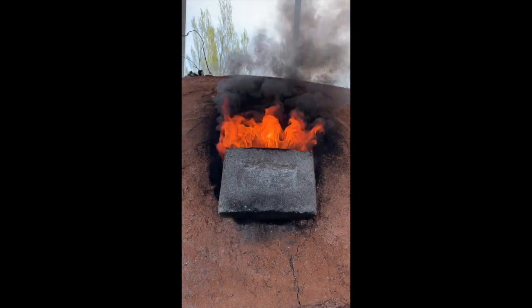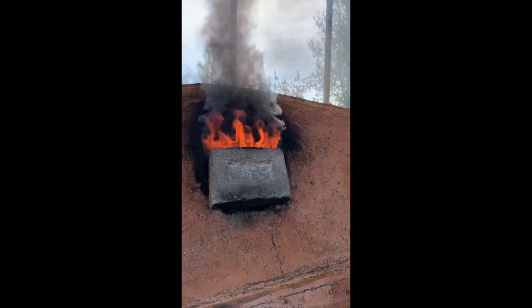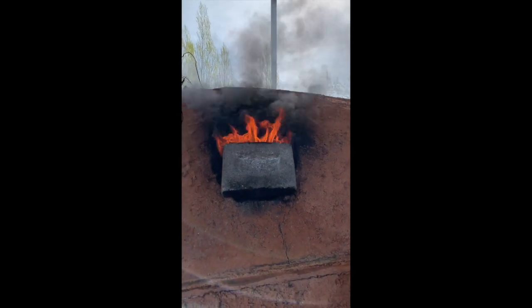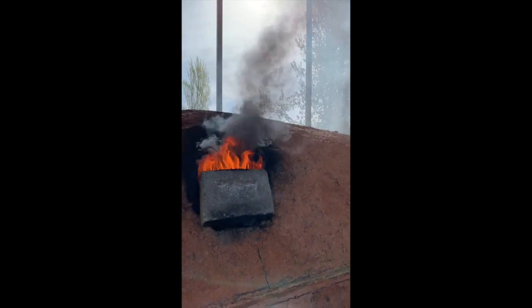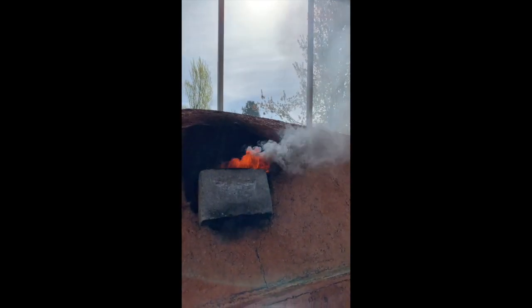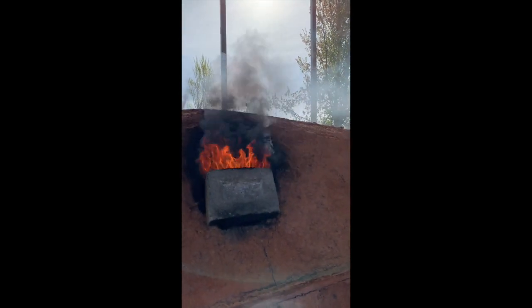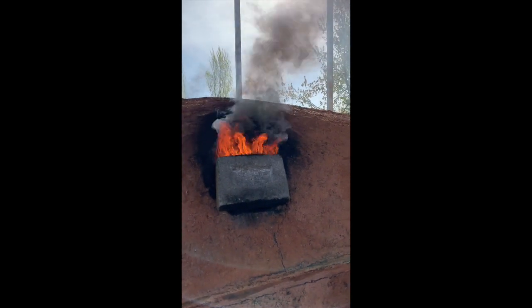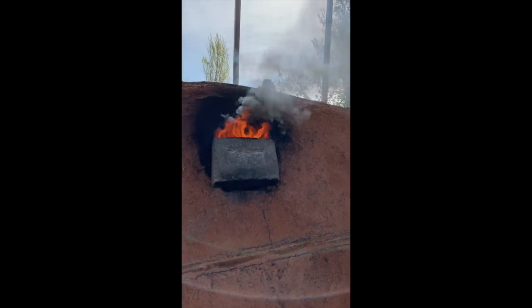I stoked the front really heavy and got a lot of back pressure. I like to think of what Chuck Hines taught me about mouse gray smoke compared to black smoke. The dampers are out enough, and even the smoke coming out here isn't really sooty black. One of the things you can count is 40 to 50 seconds of mouse gray and then it clears. That's a really good stoke, where you're really efficient. It goes back into a neutral and then oxidizing, depending on what part of the firing you're doing.